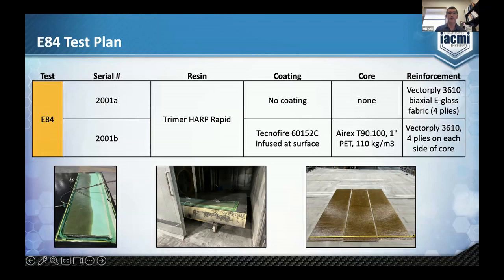I should back up for a second. The infusion of this material was kind of interesting. It took us a while to figure out how to do it reliably without air entrapment. It's a pretty thin resin. It's under 200 centipoise. It had some unique characteristics as opposed to polyester. We had to use some interesting films on the vacuum side or the vent side to keep it infusing properly.